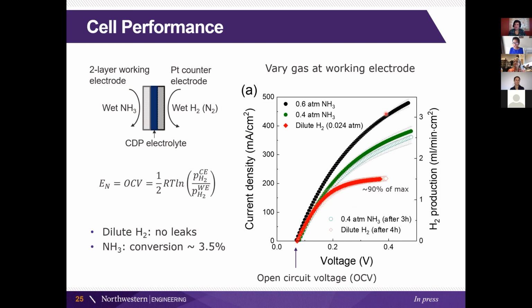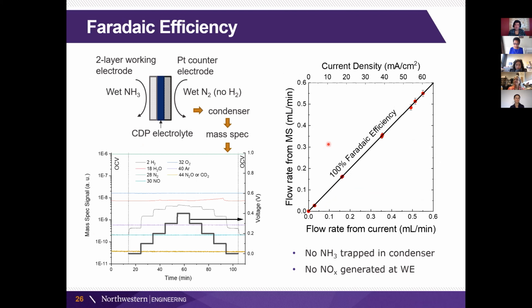When we now introduce the ammonia, you can see this is how much current we're getting out of here. And when we have more ammonia, we get more current, as you would expect. We go back to the lower ammonia concentration, and we can see that we are at almost about the same performance level, so we have reasonable stability. And this is now to show you that we indeed have 100% Faradaic efficiency.